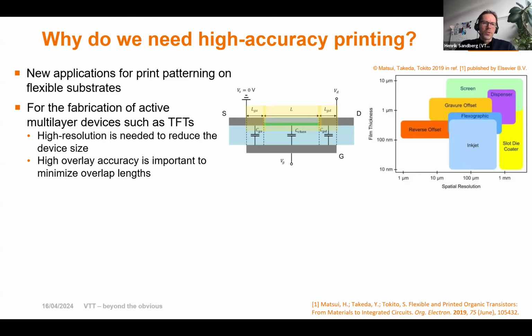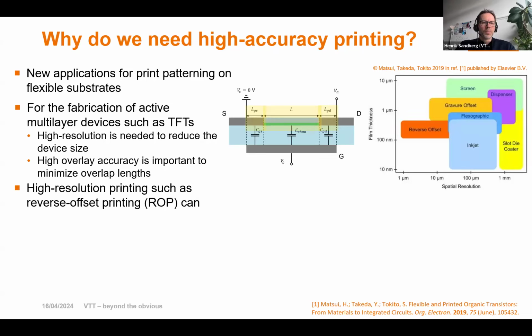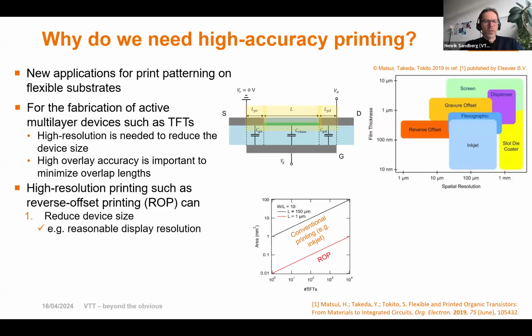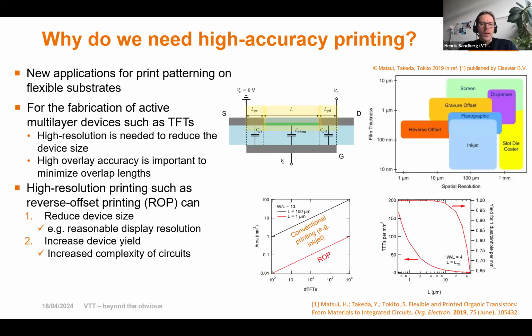There's also a very good overlay accuracy in this device, which means we can minimize the parasitic properties of a TFT, which is the overlap between the gate electrode and the source drain electrodes. And all this can be measured also in the electronic properties of the device. So it's a very good testing device. So we can reduce the device size, for example, down to a reasonable display resolution, which is required in modern devices. And we can increase the yield, and by that also increase the complexity of the circuits. And then also we can increase many of the operational features of a device.